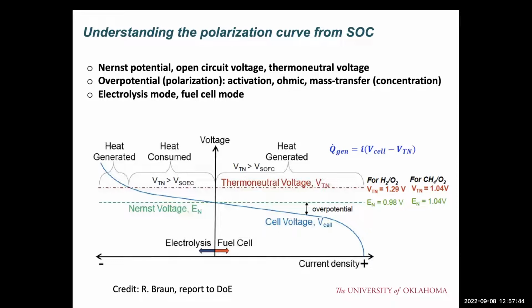As I said before, for the electrolysis reaction, we need to apply the voltage and also temperature to facilitate the reaction. Each IV curve consists of different overpotentials, or polarization resistance, which is because of the activation of the materials, because of ohmic resistance, and because of the concentration from the mass transfer of the gases. So all of the overpotentials cause the non-linear shape of the IV curve. Later I will introduce a little more about this.